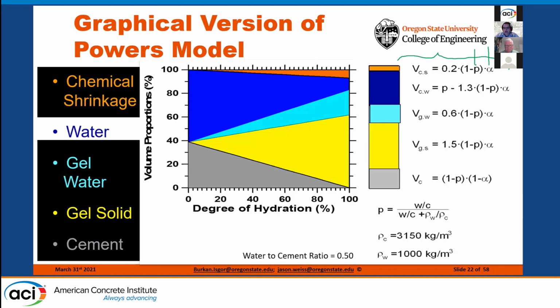So if we look at this plot, we start out before the system reacts and we have cement, shown here in the gray. We have water shown here as blue, right? And we have our initial porosity, which is about 61% in this particular case. So all of these equations are driven by putting 61% in here for P, right? And letting alpha vary from no hydration to as much hydration as we could have in the overall system. Now, as we react cement with water, the cement gets used up and is reduced. The water gets used up and is reduced. And really three things start to form.